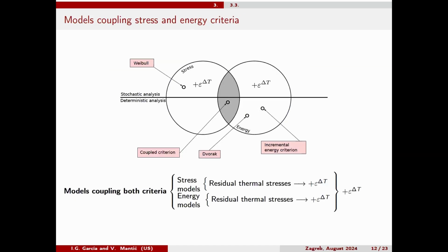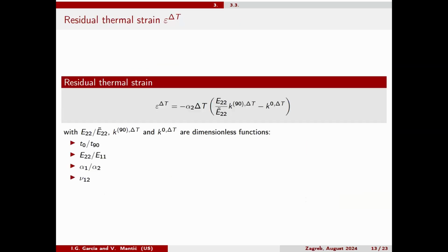So what happens with the models that combine the stress and energy models, for example, the coupled criterion? Since the effect of the residual thermal stresses is the same for the stress models and the energetic model, for the combination it is going to be the same, just adding this term here. So this term is very important, as you saw. So we are summarizing in this slide this term and the dependence of this term on the parameters.